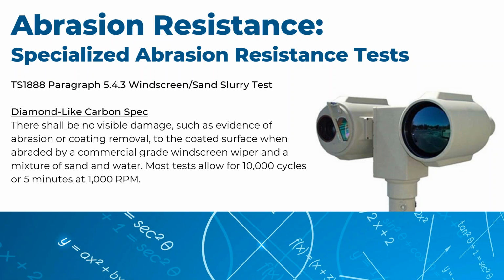So really, you don't want to see any visible damage, no abrasion, no coating removal, and none of the coating actually coming away from the surface after 10,000 cycles of a sand slurry or 5 minutes of abrasion at 1,000 RPMs. So these test setups are just like they sound. It's basically this slurry comes down over the coated optic, and you have a windshield wiper that's agreed upon and specified, and it swipes right over the optic, and the damage to the coating visibly seen prior to and after the test is what's measured.